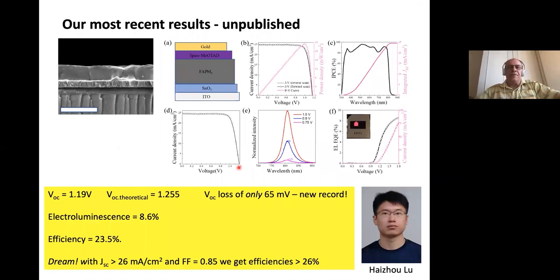So I'm coming to the very end, and that is our most recent results, and we are continuing our direction to go to as pure FAPI, as we say, formamidinium lead triiodide composition as possible. This is work by Haizhou Lu, and as you see, the cross-section looks very nice, nice grains of the perovskite. Our data, unpublished so far, we have an open circuit voltage champion of 1.19, which should be compared with the theoretical maximum of 1.25. So here we now only lose 65 millivolts. We think that's a kind of new record in terms of lowest potential loss, which also corresponds to a very high electroluminescence, maximum 8.6%, and in the solar cell current, we have around 6% electroluminescence.